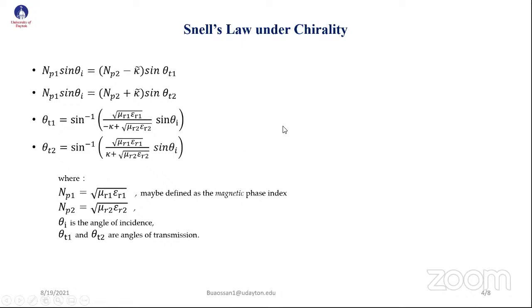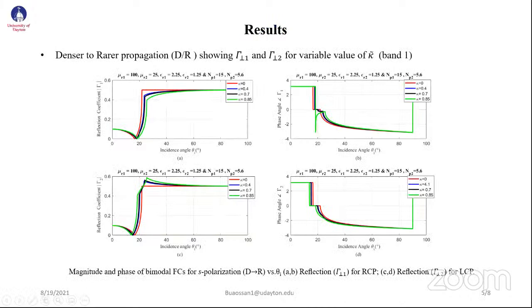We assume we have 2 cases, lossless or with dielectric loss. That means epsilon R2, the permittivity of the chiral material, will be complex. This is the denser to rarer case. We studied many cases, and this is one of them. You can see here that we have the anomalous Brewster angle. By changing the kappa value, the right circular polarization reflection coefficient shifts to the right, while the LCP shifts to the left. We also have a double inflection, which we assume is a double TIR, which we proved will also be anomalous.